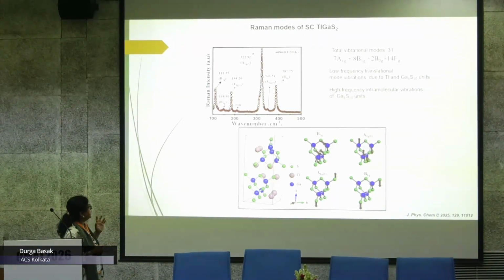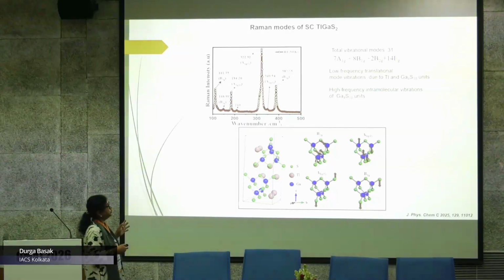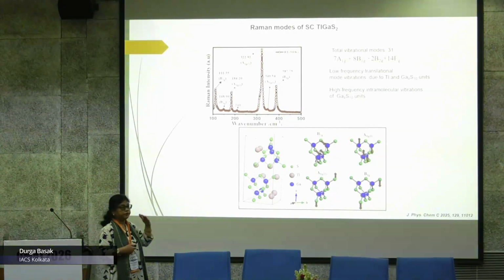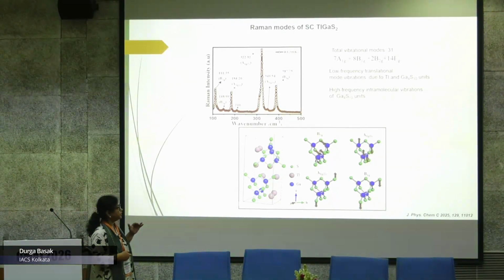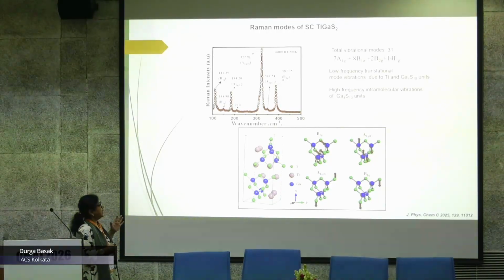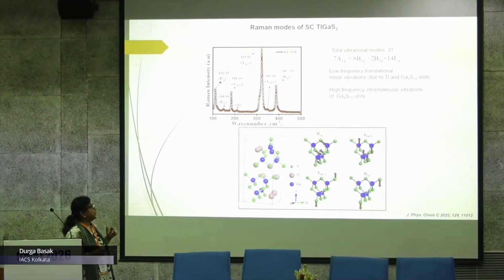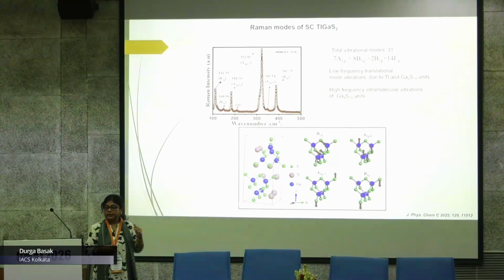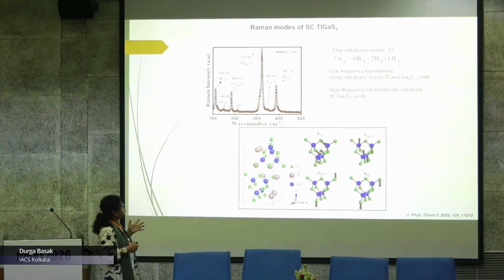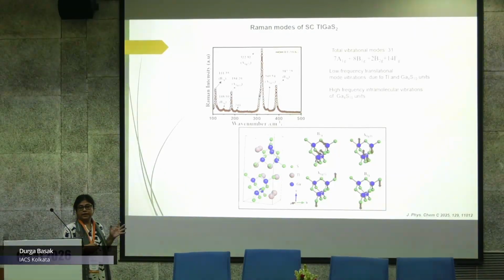But experimentally we have found that the 4 high intensity vibrational modes, the low frequency vibrational modes are due to translational mode vibration of alternate thallium and gallium S4 units, and the high frequency vibrational modes are due to intramolecular vibration in the GaS4 unit. So we have matched the theoretically calculated modes with our experimental values, and accordingly we have assigned the various vibrational modes to these particular units.